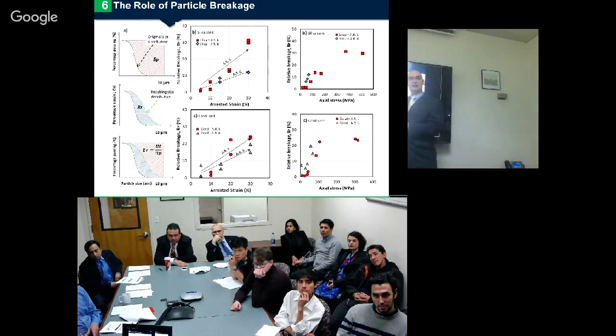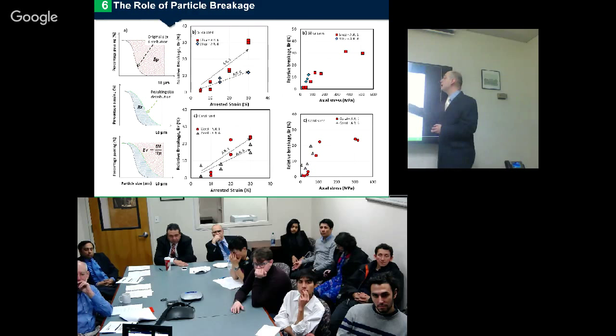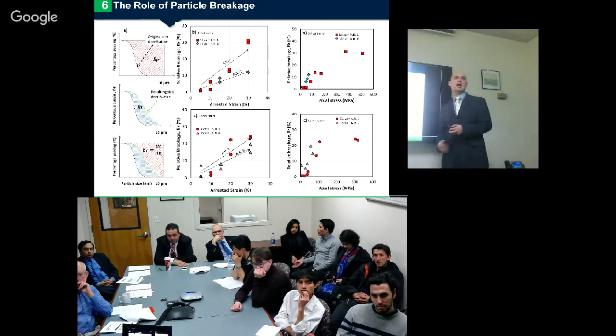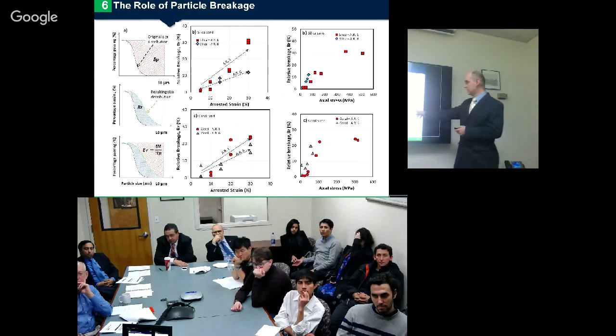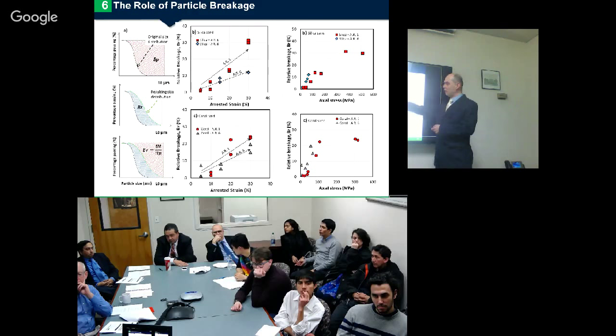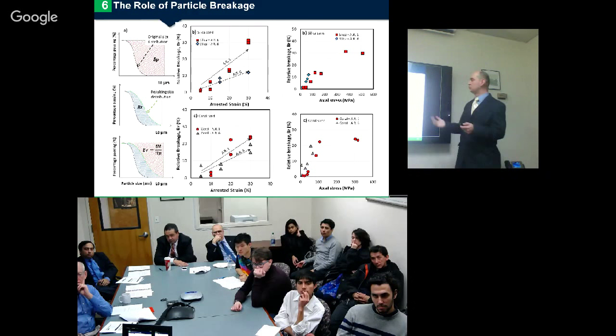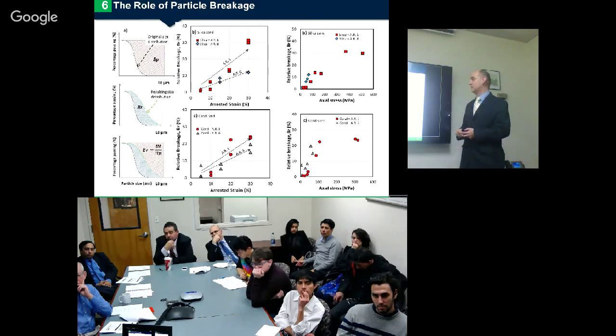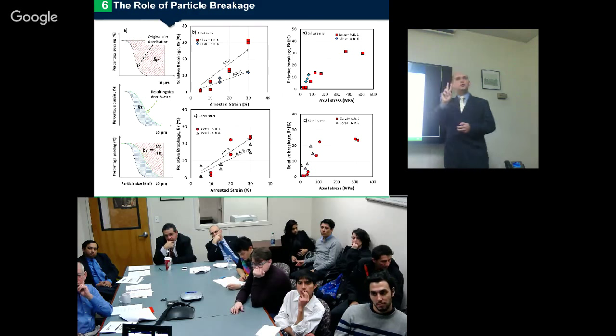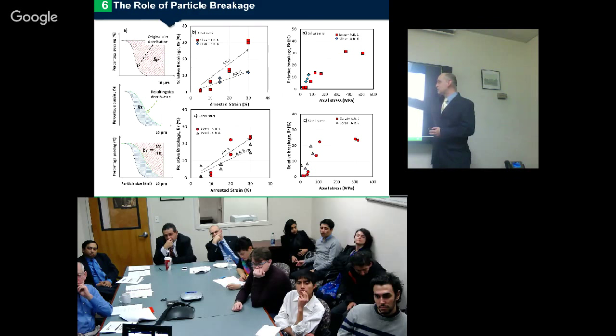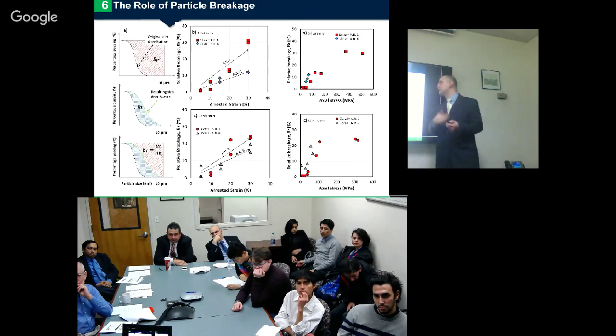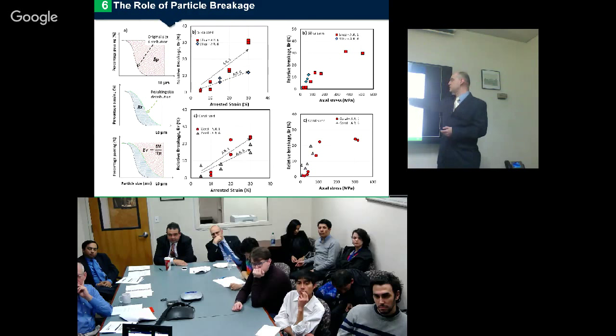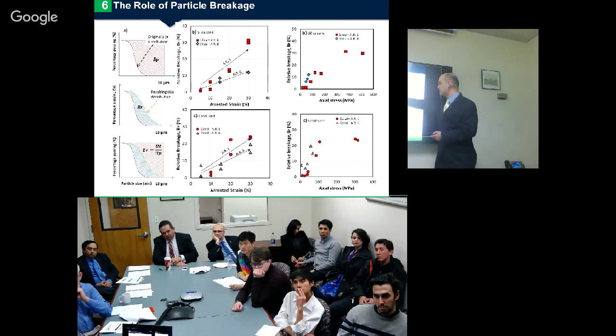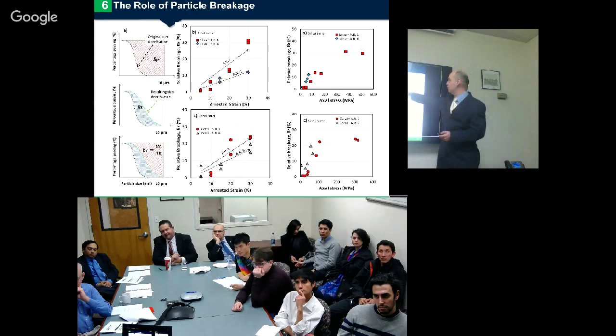When we plot the relative breakage versus actual breakage, and here we see the relative breakage versus axial stress. This is interesting: in the initial part of the test, when we load samples up to 100 megapascals of loading, those two results might be similar, and then we get something like a value of 12, 13. But now, by using smaller samples, obviously there is more actual loading, and the specimen is going to go somewhere like this, and I'm expecting to have a plateau somewhere here.